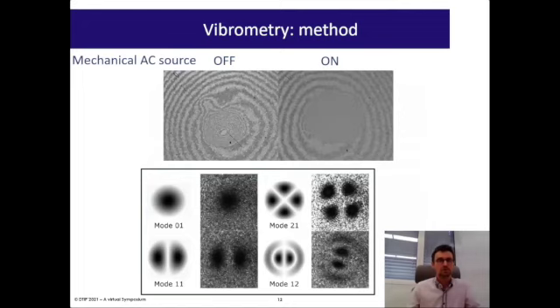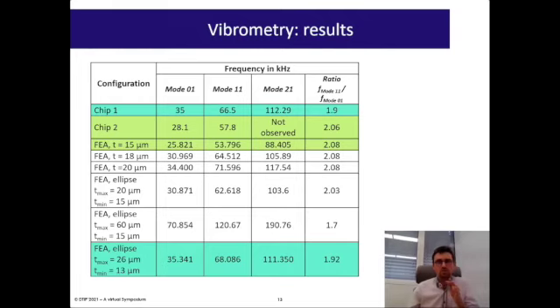Here you have two images of the fringes which could be obtained with the mechanical source off or on. When you are approaching the resonance frequency, the fringes become blurry as the membrane begins to vibrate. With this blurriness, it becomes possible to identify with precision the resonance frequency, using the contrast image from the image of fringes. We were able to identify some of the first modes of the membranes. We put in this plot both the experimental results and the simulation results.